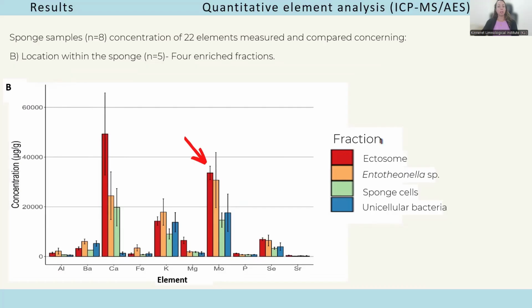To address localization, we separated the sponge into enriched fractions. These include the ectosome, which is the outer layer of the sponge, an Entotheonella enriched fraction, sponge cells, and unicellular bacteria. The highest molybdenum concentration was found in two fractions, the ectosome and the Entotheonella enriched fractions. The result was important because it narrows the biological interpretation.